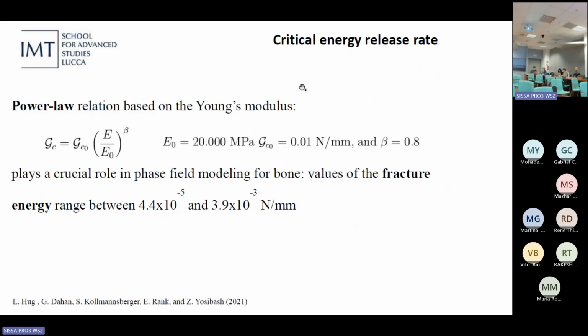Okay, the other critical parameters here for the phase field modeling of fracture are the fracture energy of the material, which is considered with this formula, derived from previous work by Professor Yoshiba. It is considered as a power law of the Young modulus inside the material, so it is again a non-uniform distribution inside the domain.